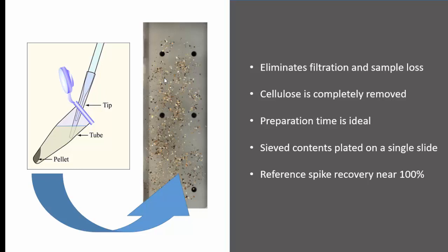This eliminates filtration and sample loss. The cellulose is completely removed. Preparation time is very short. We can do this in just a few hours, taking a sample from the initial raw sample collected off the sieves to a sample that's ready for analysis. All the sieve contents are now plated on a single slide, and we have reference spike recoveries that are near 100%.